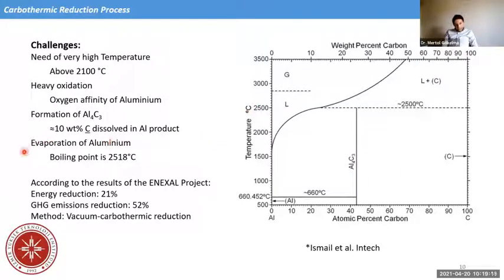And the fourth challenge is evaporation of aluminium, because for good reduction, we need temperatures close to 2500 degrees, and a bit above 2500 degrees, aluminium already evaporates, already boils. So there will also be a lot of evaporation of aluminium, and this also increases oxidation.